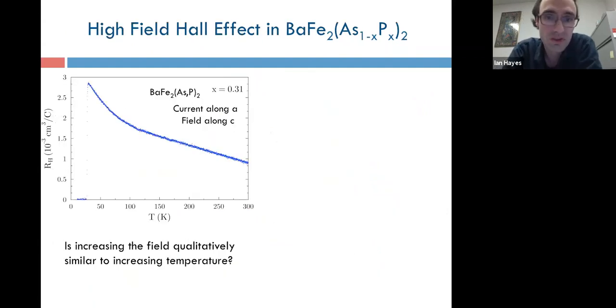So start with optimal doping. This is the Hall coefficient at low fields for optimally doped barium-122, 31% phosphorus substituted. And I should start by saying that for all the data I will show you, the field-current configuration is that current is passed in the plane, in particular along the a-axis, and field was applied along the c-axis.